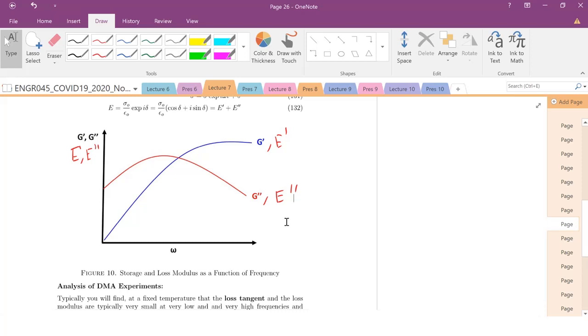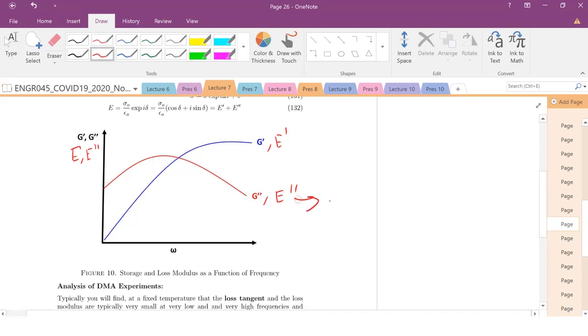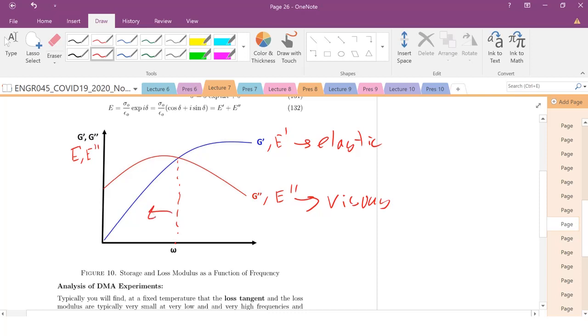This is a really important parameter for polymers and viscoelastic materials. You can tell at what frequencies a material will behave like a solid versus a liquid. E-double-prime is the viscous response and E-prime is the elastic response. Behavior is dominated by whichever curve is higher, and there is a crossover point — to the left of the crossover, the viscous term dominates.